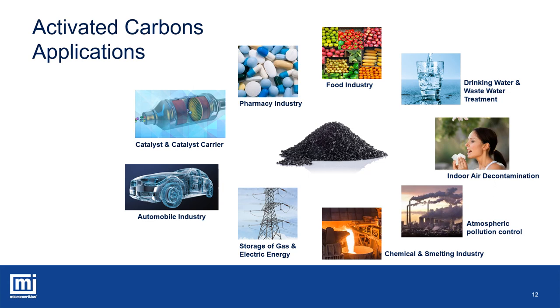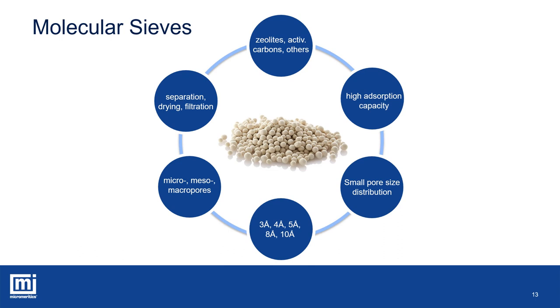So as we have talked about zeolites and activated carbons, what are molecular sieves? In comparison to the two previous examples, this is strictly speaking not a material class, but the functional designation of a group of substances characterized by high adsorption capacity for gases, vapors, and dissolved substances with specific molecule sizes. Molecular sieves have a small pore size distribution and are especially suitable for separation processes, as pore diameters are similar in size to small molecules and large molecules cannot enter. Most prominent molecular sieves are zeolites, classified by pore size in angstroms. Application examples include drying of organic solvents, oxygen and nitrogen separation from air, and removal of H₂S from natural gas.